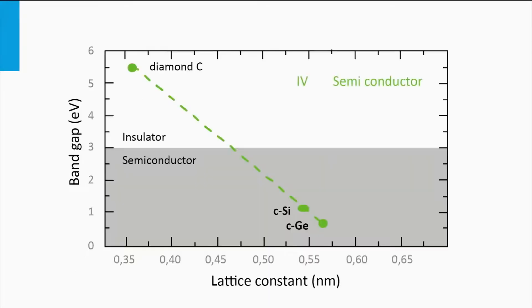In the next graph we plot the band gap of crystalline carbon, silicon, and germanium versus the lattice constant. Crystalline carbon is another name for diamond. We indeed see that the band gap is very large for diamond, as diamond has the smallest lattice constant. In a simplified representation, the larger band gap can be considered as a result of a larger overlap of the original sp3-like orbitals of the neighboring atoms. A larger overlap induces a larger splitting of the energy levels of the bonding and antibonding levels.